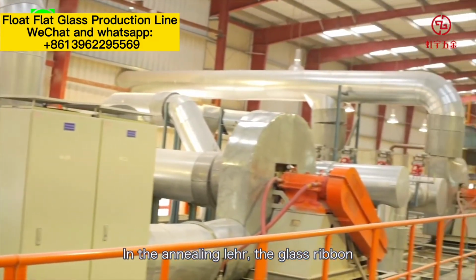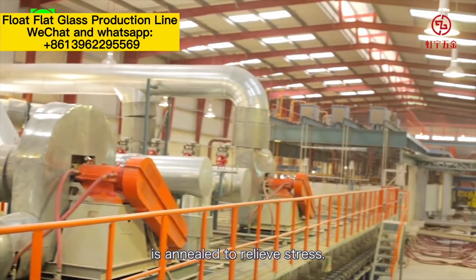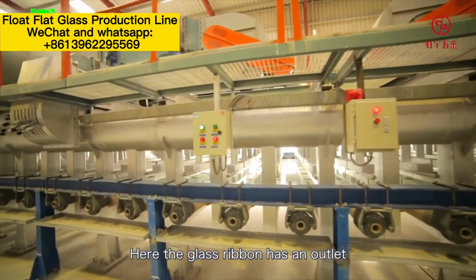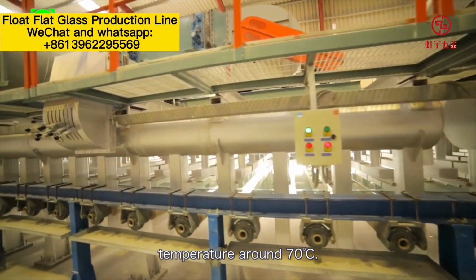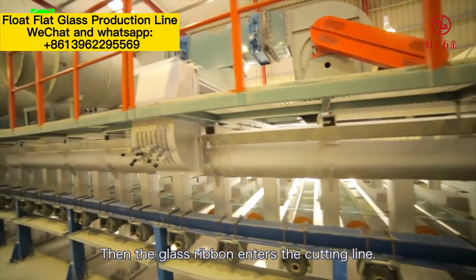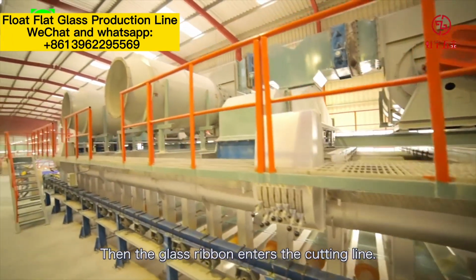In the annealing lehr, the glass ribbon is annealed to relieve stress. Here, the glass ribbon has an outlet temperature around 70 degrees Celsius. Then the glass ribbon enters the cutting line.